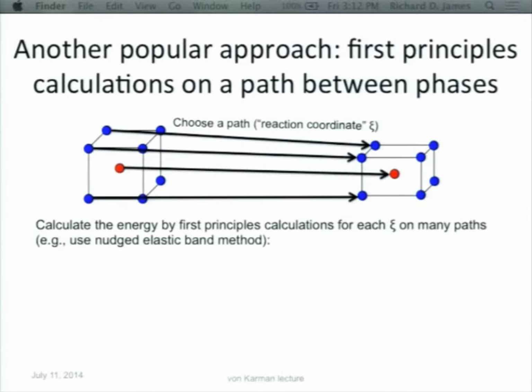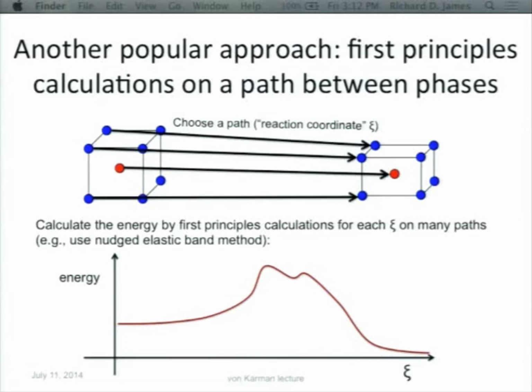And you do this for many, many paths between these two, and in fact, there are mathematical methods, for example, the nudged elastic band method, which helps you find the lowest energy barrier between those two phases. So you find this lowest energy barrier, and the height of that should correlate with the hysteresis. That's a belief.